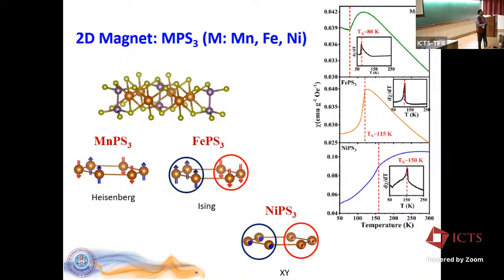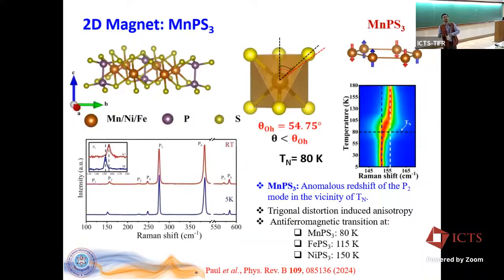Now, before I head out, I showed in the previous slide the bulk measurement to assure you that there is indeed antiferromagnetic ordering, and to tell you the antiferromagnetic ordering temperatures, the Néel temperatures, right? Now, how do we know that there's something happening in Raman? So here is the first example of MnPS3. This is room temperature data, the red one, and this is the low temperature 5 Kelvin data.